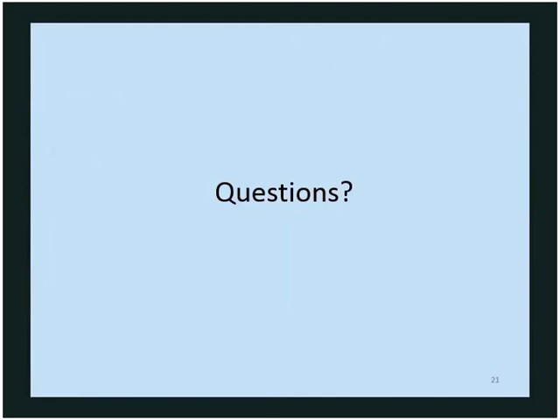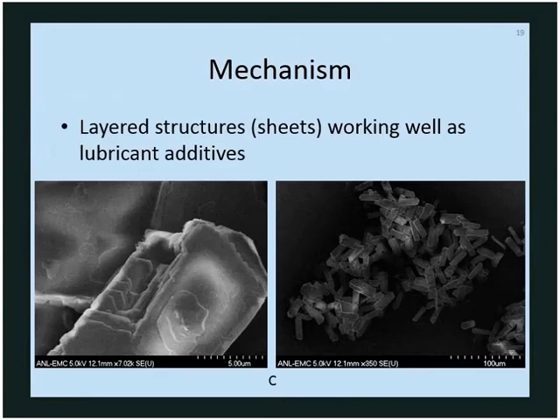Can you say again if the layered structure is better, or how it helps? Yeah, this layered structure, as you can see, is better than the phosphotungstic acid in that it forms more of a layer and protection between the steel ball and the flat. So in forming a tribochemical film layer, it would provide better insulation and better anti-wear properties. And this is just a closer up view of it.